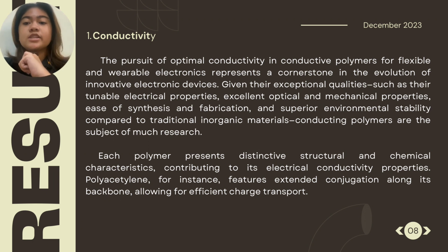Similarly, polyaniline or PANI offers promise with its solubility in a conducting state, achieved by doping with large organic anions like dodecylbenzene sulfonic acid or DBSA, or camphor sulfonic acid or CSA. This enhances its processability, especially in solvents like chloroform and m-cresol. PANI's side chain anions play a pivotal role in reducing interchain interactions, aiding in its application in both organic solvent and water.